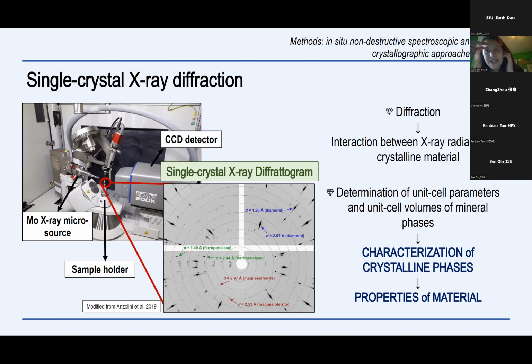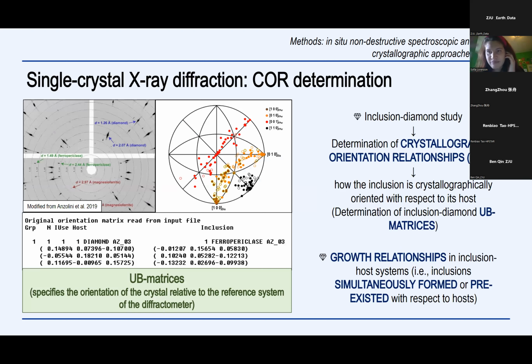But in diamond study, in which way do we use single crystal X-ray diffraction? Single crystal X-ray diffraction is mainly used for two different applications. The first application is the determination of the crystallographic orientation relationship that can exist between inclusions and their diamond host. These crystallographic orientation relationships tell us how inclusions are crystallographically oriented with respect to their diamond host.